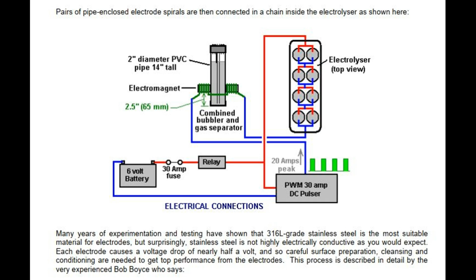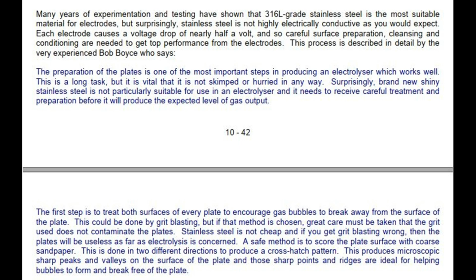Many years of experimentation and testing have shown that 316L grade stainless steel is the most suitable material for electrodes, but surprisingly, stainless steel is not highly electrically conductive as you would expect. Each electrode causes a voltage drop of nearly half a volt, and so careful surface preparation, cleansing and conditioning are needed to get top performance from the electrodes. This process is described in detail by the very experienced Bob Boyce, who says, "The preparation of the plates is one of the most important steps in producing an electrolyzer which works well. This is a long task, but it is vital that it is not skimped or hurried in any way.